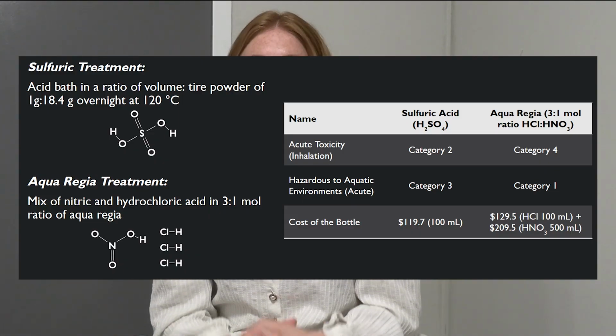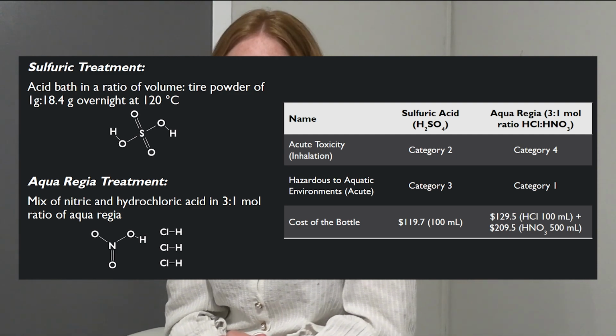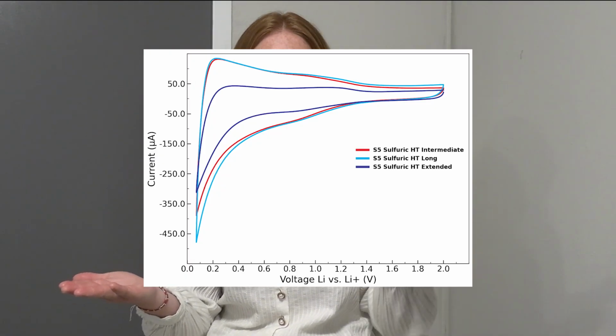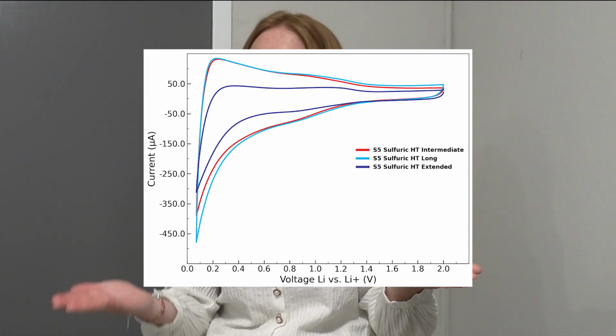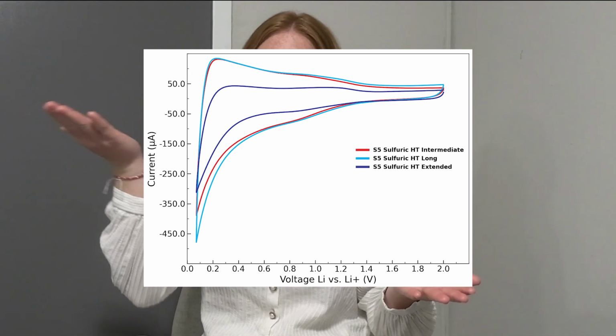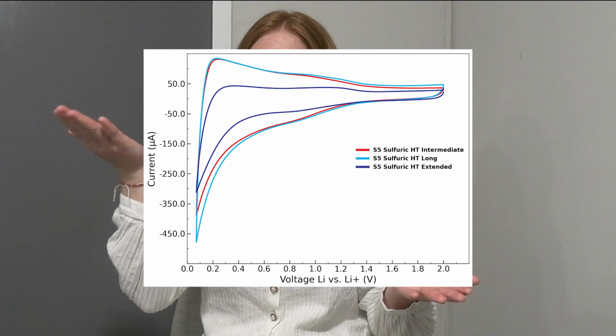You may be wondering, what was the point of all of that? Well, I'm here to tell you that we were able to optimize both the acid treatment and the heat treatment to make hard carbon out of our tire material. The best acid treatment was a sulfuric acid bath at 120 degrees Celsius overnight. The best heat treatment ended up being a set of 2 steps. First, you heat up the material at 400 degrees Celsius in air for an hour, and then you heat it up to 1200 degrees in nitrogen for 3 hours.